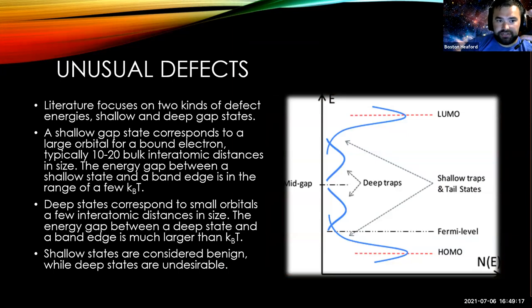And usually the literature focuses on two kinds of defect energies, shallow and deep gap states. A shallow gap state corresponds to when an orbital for a bound electron is relatively large, 10 to 20 bulk interatomic distances. And the energy gap between a shallow state and a band edge is typically on the range of a few kBT. Whereas deep states correspond to small orbitals, and the energy gap is typically quite a bit larger than kBT.